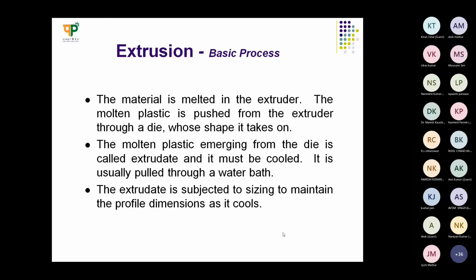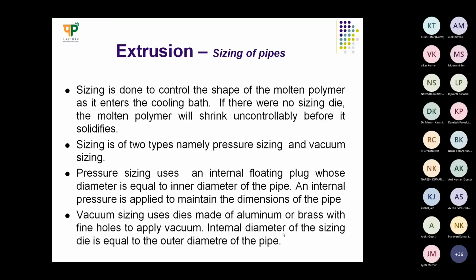Any profile you have to do the sizing, then only you will have a uniform size. Sizing is done to control the shape of the molten polymer as it enters the cool bath. If there were no sizing die, the molten polymer would shrink uncontrollably before it solidifies. So therefore it will collapse if you don't have sizing.